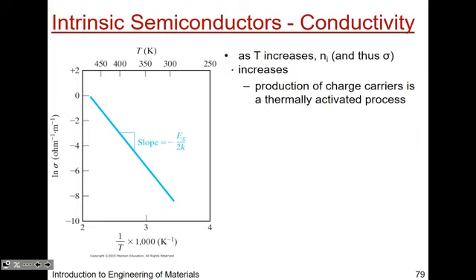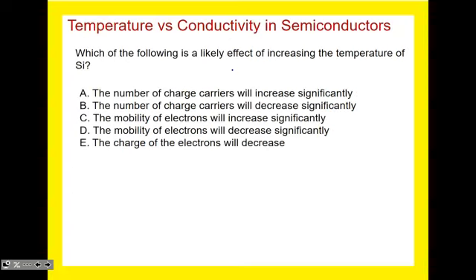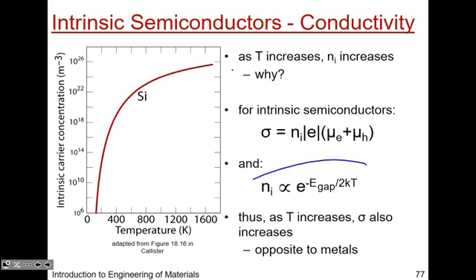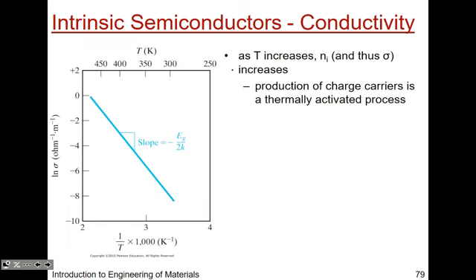So, right. So then you can backtrack all this information out and say, okay, if I plot the log of my conductivity of my material, I can just put down a 2-point probe and measure the conductivity within my material. I can plot something that looks like an Arrhenius type relationship and backtrack out the band gap, this Eg, okay? And based on this relationship, we can see that the slope is negative of the band gap divided by 2 times the Boltzmann constant, okay? So it's a thermally activated process.